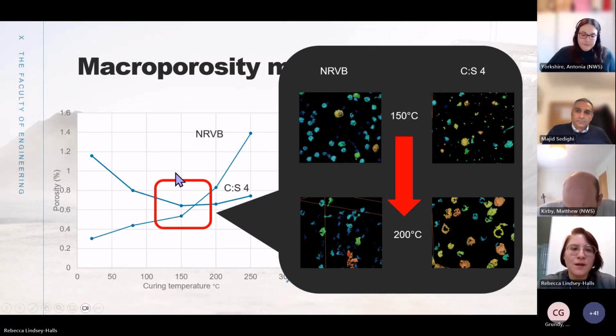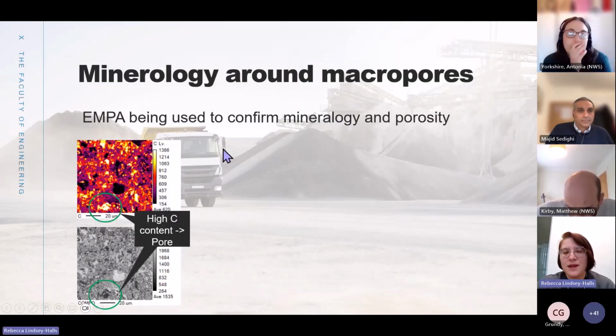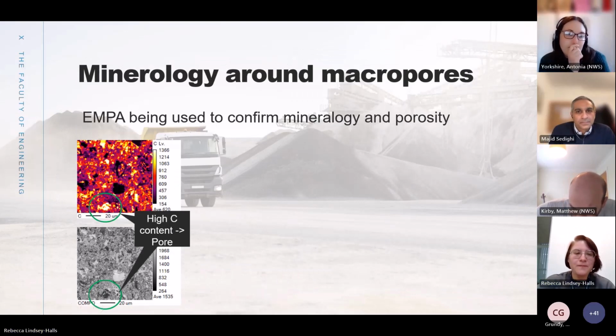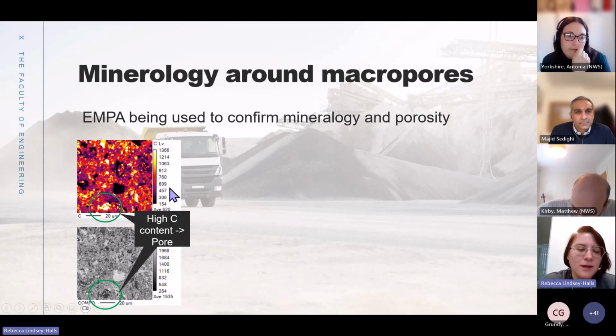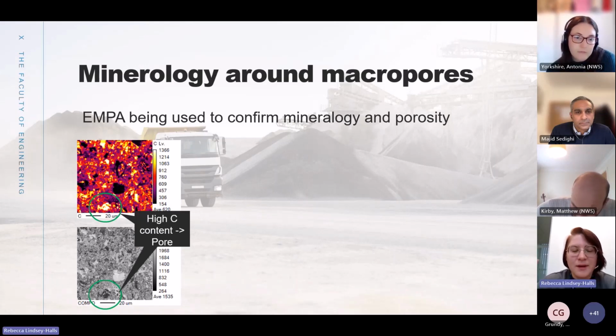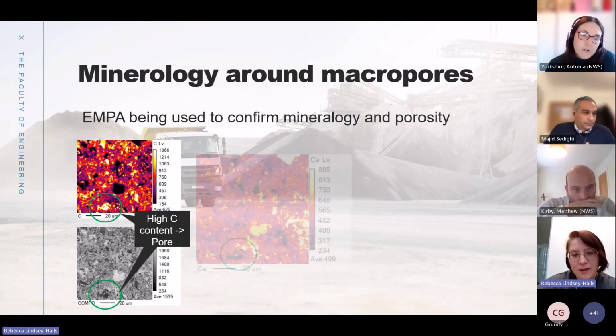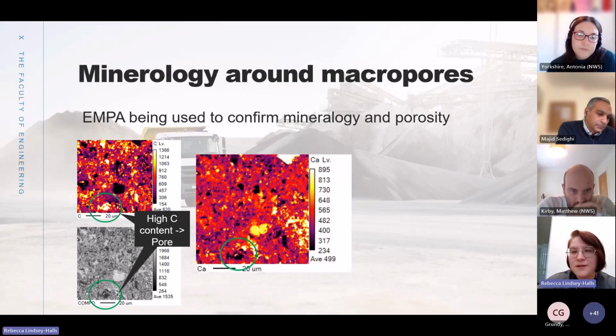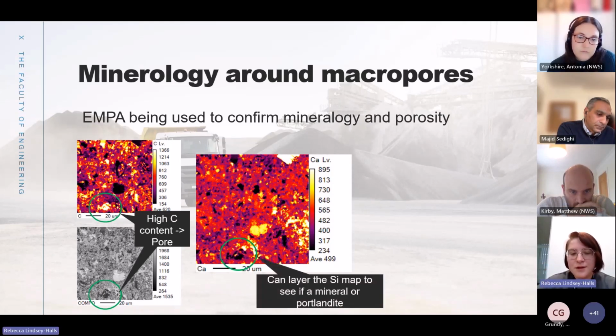And then here are some pictures from the EPMA measurements. This is being used to confirm the mineralogy and the porosity. The pores can be confirmed because you get this high carbon content. They're embedded in resin, which is high carbon, so you basically look for that. Then I look at the elemental map of calcium, and there's no calcium present, so that pretty much confirms it's a pore. Then I lay the silicon map over the top to see if it is an actual calcium silicate mineral